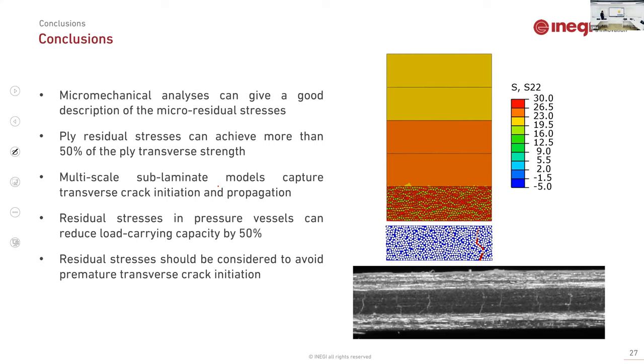This kind of sublaminate modeling approach is also very interesting to analyze how the failure can be initiated, considering the constraining effect of the adjacent layer. It's very different. If I only simulate one layer versus a layer embedded in a sublaminate, the local stiffness that is added to this ply by the adjacent layer will change locally how it will behave. So it is a relevant effect that needs to be considered.